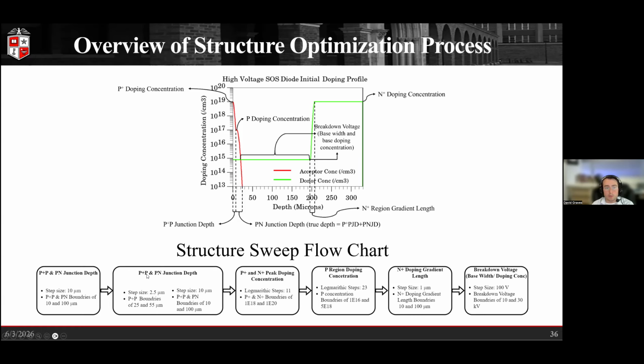We then moved on to a P plus P and PN junction depth sweep again, where we're looking at the depths again. We refined it and did smaller steps in order to converge on a more accurate, more ideal solution. Then we moved into the P plus P and N plus peak doping concentrations. And then we moved into the P region doping concentrations. Then we looked at the N doping gradient, so this distance from our N plus N junction all the way to where we hit our substrate. And then we looked at the breakdown voltage, which would alter our width here and the doping concentration.